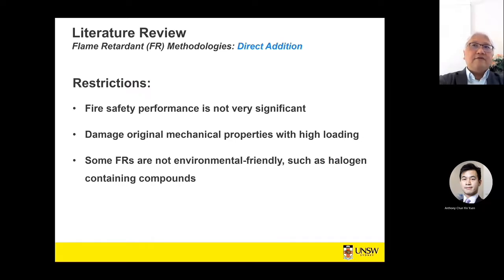Also, by infusing some of these flame retardants in the polymer matrix, the original content of the material is reduced. To give you an example, in a pristine polyurethane foam, you have 100% of this material. If you take out 20% and replace it with 20% of the flame retardant, a lot of the mechanical properties are lost. And this is demonstrated by some of the testing that we have carried out. Also, some of these flame retardants being introduced are not environmentally friendly. For example, they do contain a lot of halogen or even bromide-containing compounds as well.